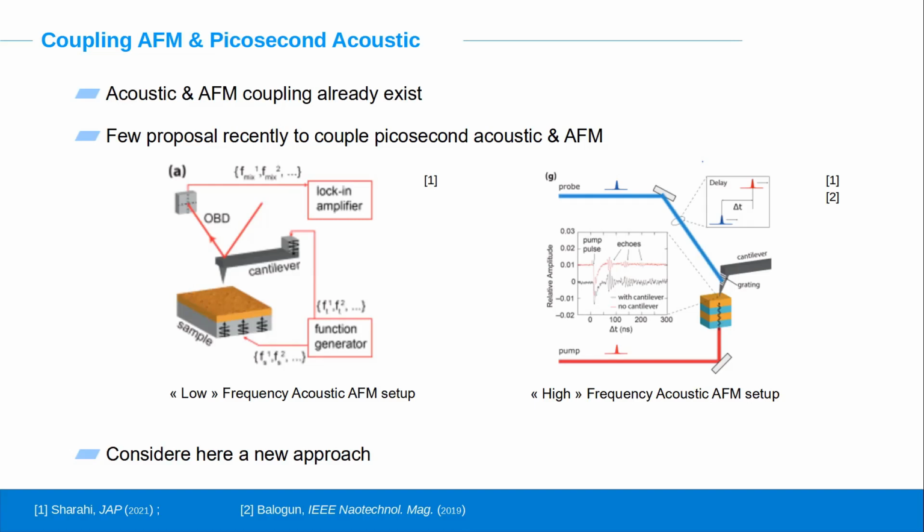And using such a high frequency setup, people were able to reach a lateral resolution of about 100 nanometers, a similar value to the one obtained coupling picosecond acoustics and near field optical microscopy. And so here we want to consider a new approach, ideally where there is absolutely no contact between the laser beam and the sample.